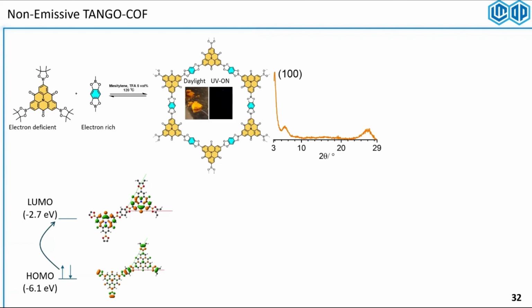But it turned out to be totally non-luminescent. Essentially just dark yellow sad powder, so to say. And we found that I neglected the electronics of the system when I designed it, because we had this very electron donating tetrahydroxybenzene in the center as the linkage, and the electron withdrawing Tango core, which has 3 carbonyl groups, 3 boronic acid groups. And when we excite this system, the electrons would flow from the electron donating core, HOMO, to the LUMO of the electron withdrawing core. And having this charge transfer excited state is totally non-luminescent for us.